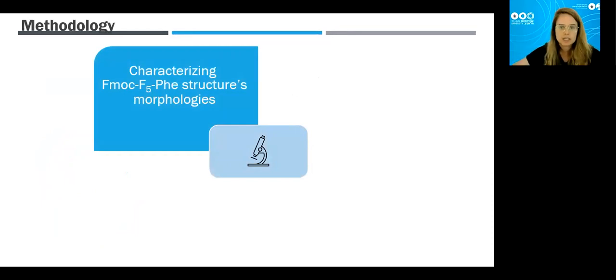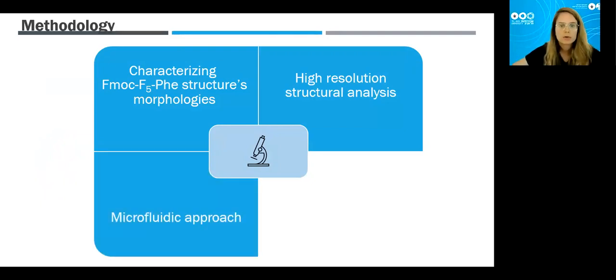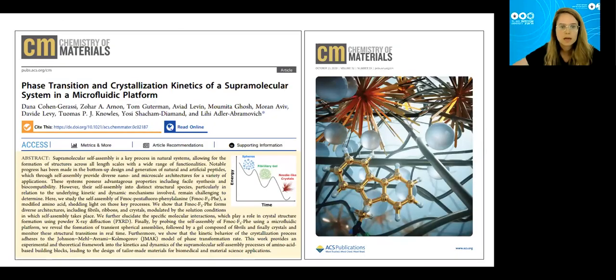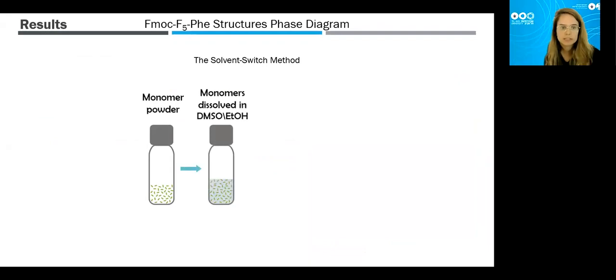This study was recently published in Chemistry of Materials and selected for the journal front cover, in collaboration with Professor Knowles' group from Cambridge University and Dr. David Levy from the Wolfson Research Center at Tel Aviv University. To prepare the building block using the solvent switch method, monomers are dissolved in organic solvent such as ethanol or DMSO, then diluted in aqueous solution to initiate spontaneous self-assembly creating a hydrogel. I used a 96-well plate to systematically study the effect of different conditions, varying the organic solvent ratio from 10 to 100% and the amino acid concentration from 0.2 to 10 g/L.